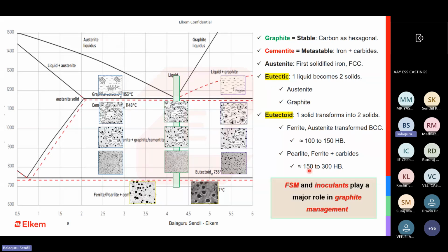So I would like to point out that FSM and inoculants play a major role here in graphite management. Your FSM has silicon, and your inoculant also has silicon. So we need to understand that having more inoculant or more FSM is not always ideal, because it will influence the carbon equivalent. It might change the casting from this to this or from this to this, which is not an ideal situation.